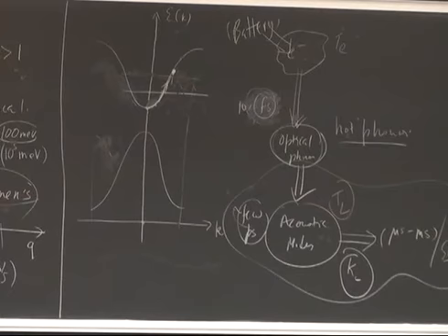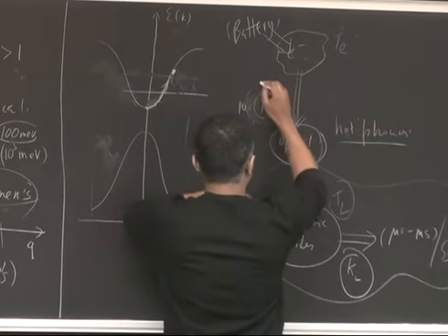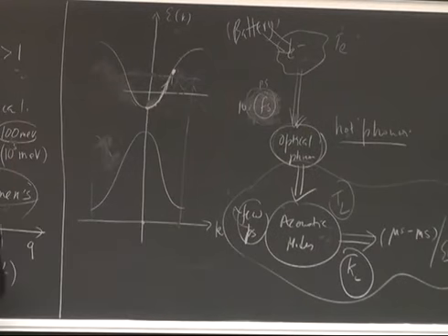How fast would that be? Oh yeah, this can be tens of femtoseconds, but of the order of picoseconds, and this scattering rate is also slightly longer, but also of the order of picoseconds. It's not milliseconds or microseconds. The thing is, every emission into this mode carries away a lot of energy, while every emission into that mode carries away very little energy. So even though the time scales are similar, these modes are much more potent in carrying the energy out. You have 1,000 of those combining to give you only one of those. So the time scale is not as important as the number. The energy dissipation is much more.